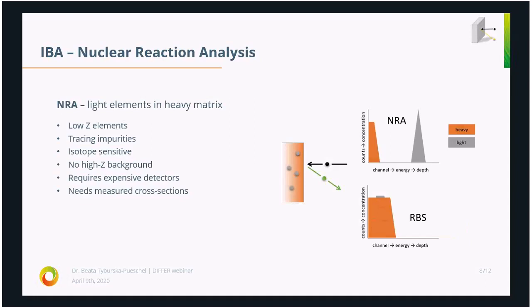So NRA is used mostly for low Z elements, maximum to mass 15. You can use it to trace impurities like, for example, oxygen and nitrogen. It's also isotope sensitive, so you can see carbon 13, carbon 12, if you are interested in it. Then there is no high Z background, because that background we can actually remove. It's true it requires expensive detectors, and you need to measure cross-section. If you have some more exotic applications, then I would have to first measure cross-section for you to be able to perform those experiments.